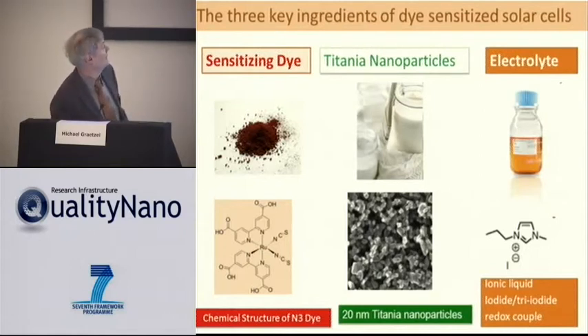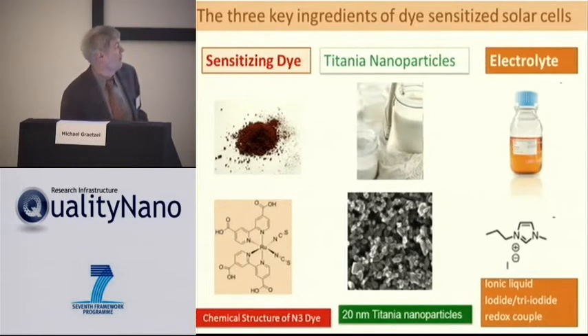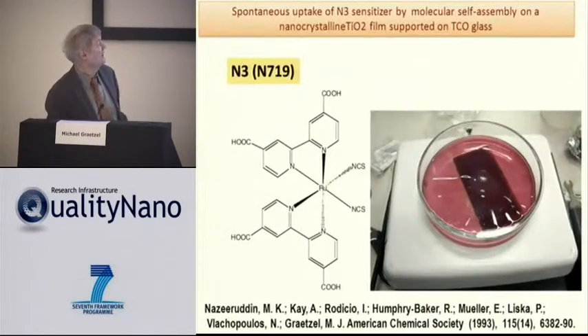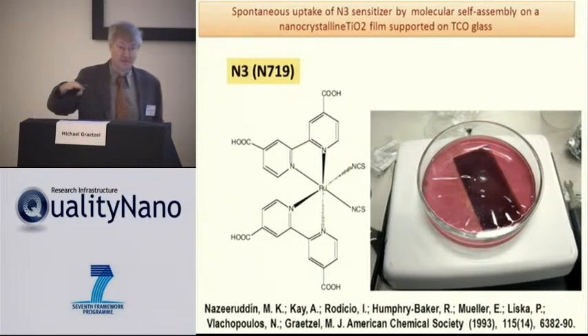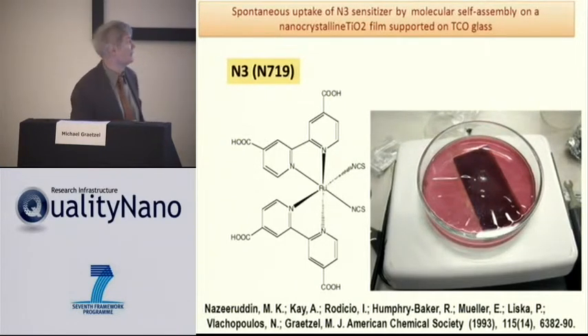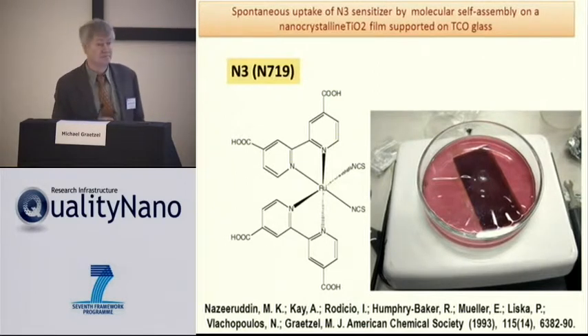And this is the paste I mentioned to you, and this is the very often used ionic liquid that serves as a redox shuttle to move the charges from the surface of the nanocrystals to the counter electrode. And so here you see that spontaneous pickup. This is one of those glass sheets with the nanocrystalline film on top. And just dip it in the red dye solution, it gets very dark.